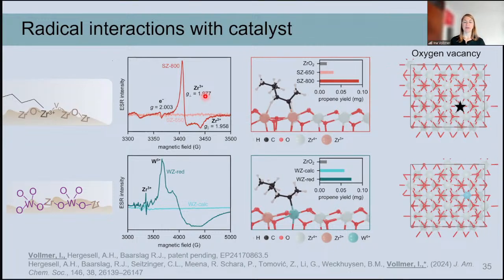Yeah, so of course we did already try to do that by creating two different materials, one with less defects and one with more defects, as you can see here. So we have the sulfated zirconia treated at 650 degrees Celsius and the one treated at 800 here in the darker color. And we can see that this material that does not show many defects is also not mechanocatalytically active.